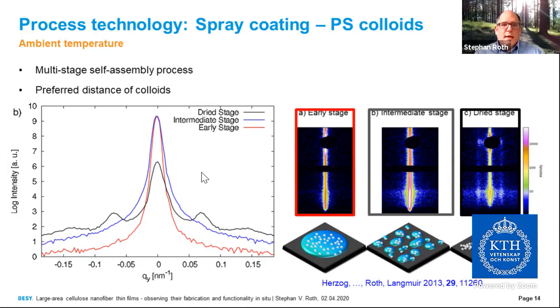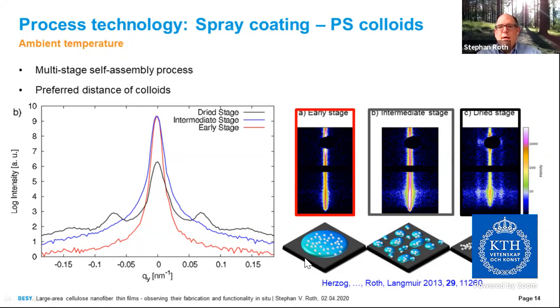Averaging curves from the three regimes: early stage in red shows a sharp middle peak; intermediate stage in blue shows the beginning of side peaks; in the late or dry stage (black) the side peaks are very well pronounced. The corresponding two-dimensional scattering patterns and a pictorial view show that: initially we have a liquid layer or pool of nanoparticles in water; the solvent evaporates and the liquid breaks up; colloids are confined in smaller droplets; then the water evaporates from the smaller droplets, leaving an ordered structure confirmed by these out-of-plane pseudo-Bragg peaks.